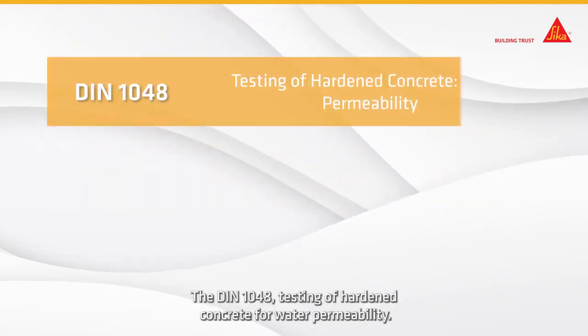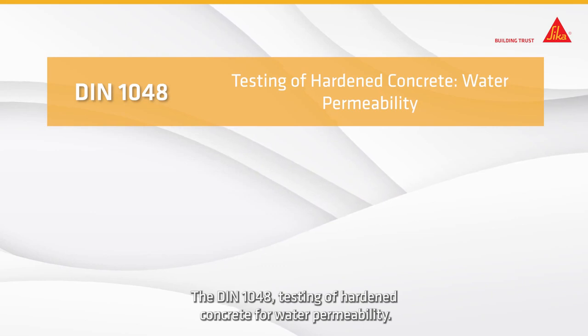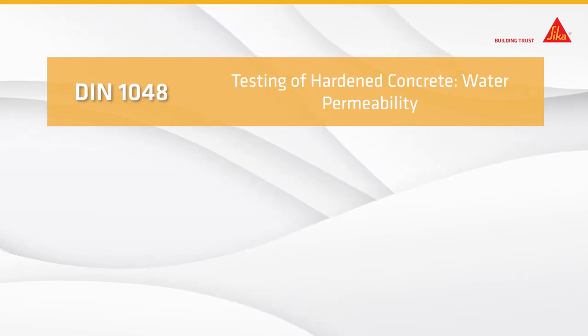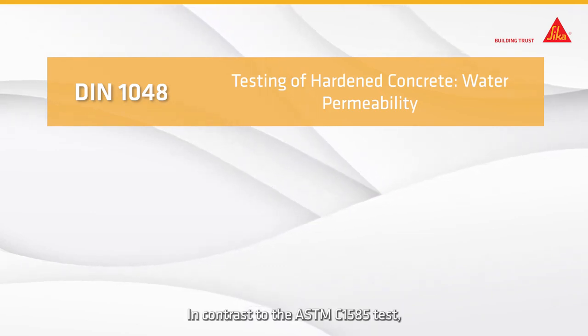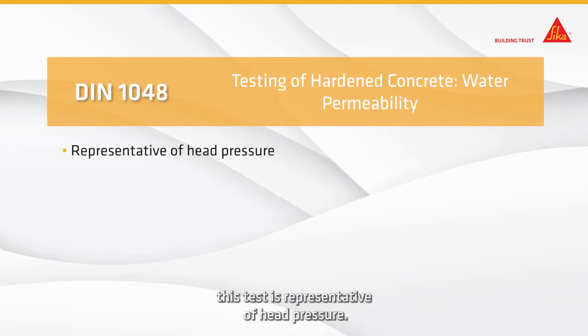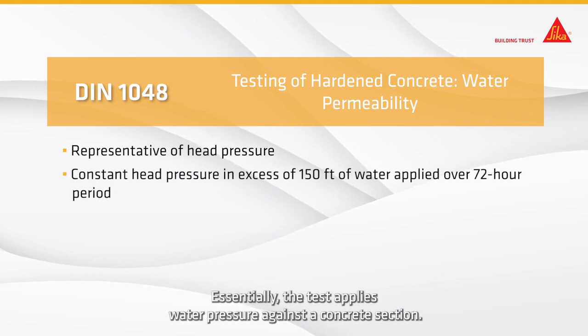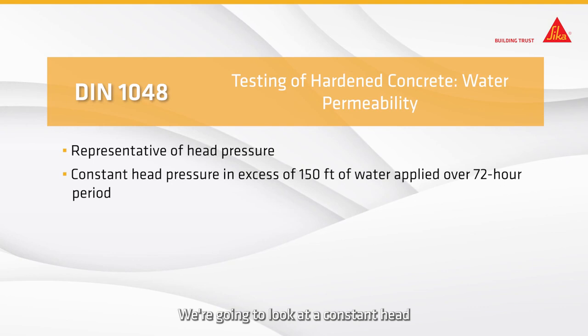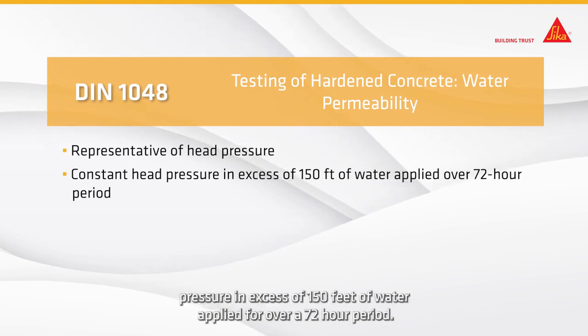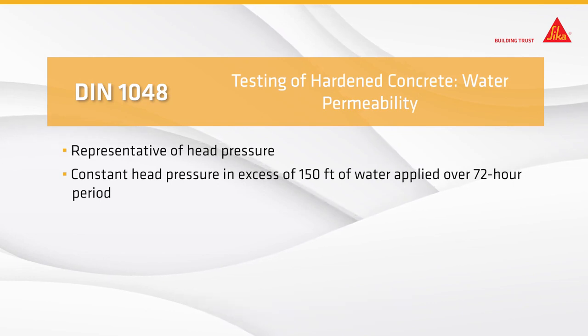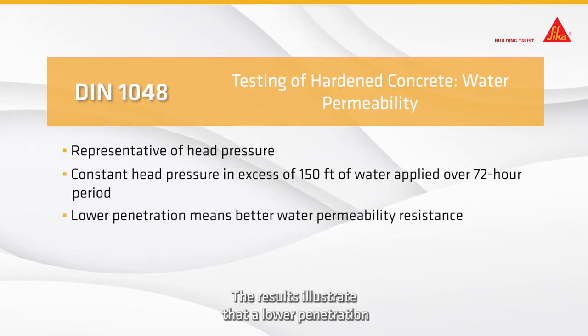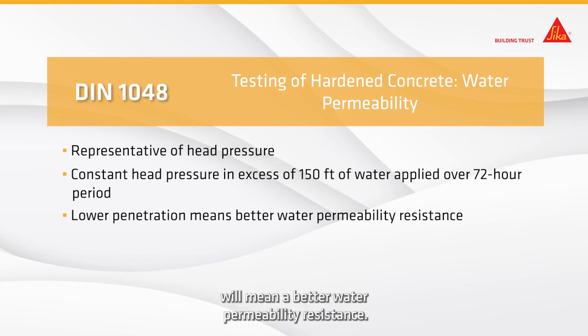The DIN 1048, testing of hardened concrete for water permeability. In contrast to the ASTM C1585 test, this test is representative of head pressure. Essentially, the test applies water pressure against a concrete section. We're going to look at a constant head pressure in excess of 150 feet of water applied for over a 72-hour period. The results will illustrate that a lower penetration will mean a better water permeability resistance.